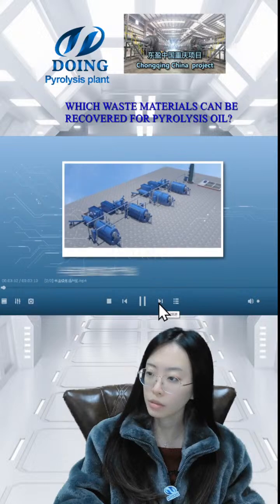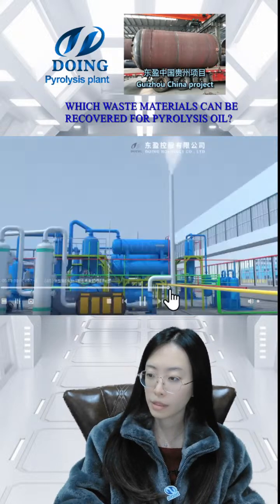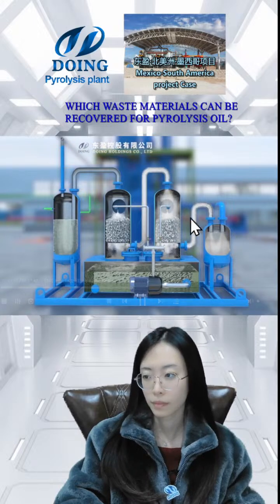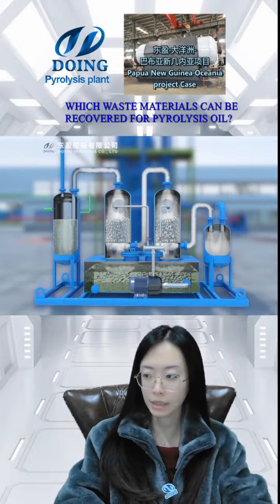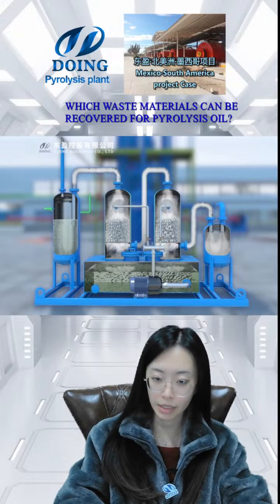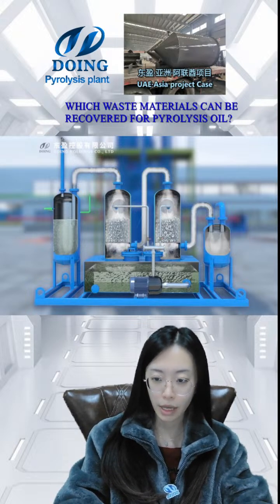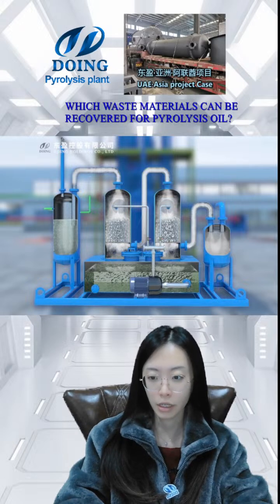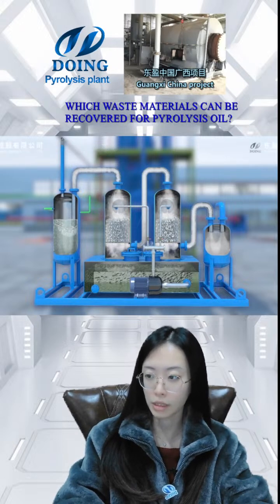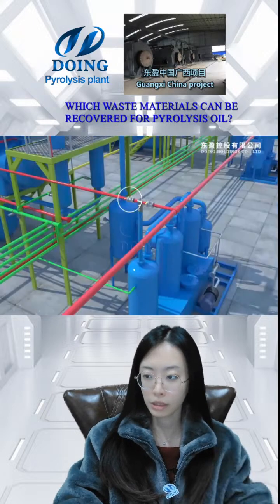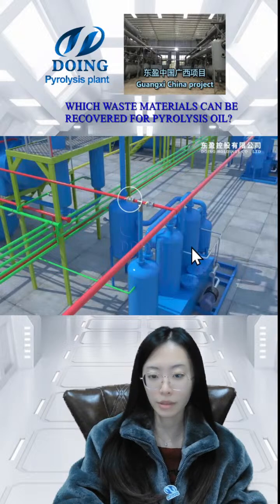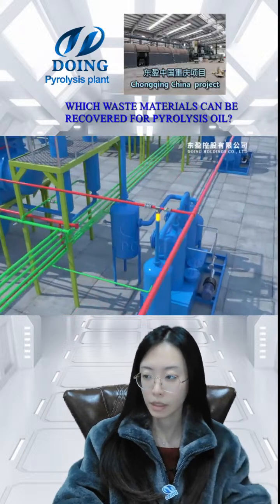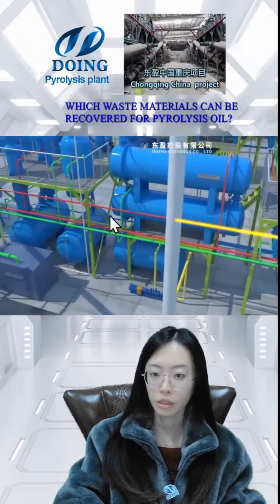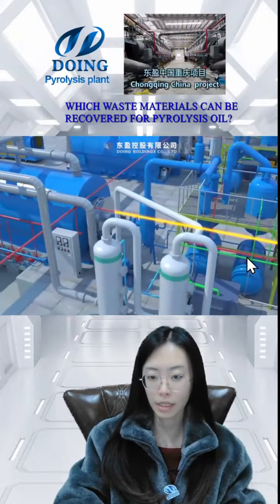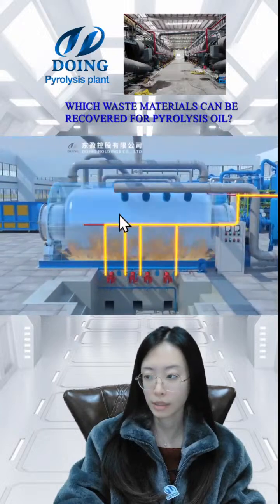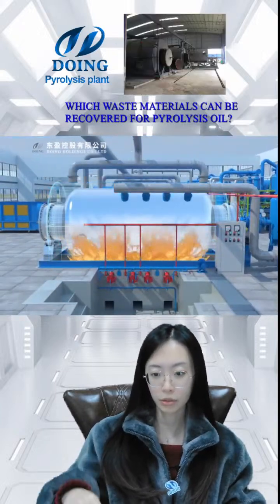Or it's clearer to see in this batch type pyrolysis plant. The odor removal system is our patent device, because if we burn the tail gas directly, there will be some bad smoke, and the hydrogen sulfide is corrosive to our furnace. So we use this to purify them. It has sodium hydroxide inside. Then after purification, it goes back to the furnace, using the tail gas burner to heat the furnace. This is the two applications of the gas.